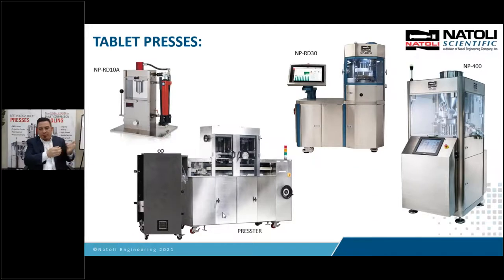So you apply the material into the die cavity or use a feed shoe, and you tell the computer software, which is the AIM data acquisition system, what press you're trying to emulate. So if you try to emulate a Natoli MP500 at 50 RPM, it's going to know the velocity, the dwell time, and the loading rates. And then this carriage is going to go through that whole compression process, but on a linear fashion. So making one tablet at a time, it's going to make a tablet at speed of production, and this machine reaches up to 2 meters per second. We ran most of our studies at 1 meter per second because that's a typical range for manufacturing, but you can go up to 2 meters per second.